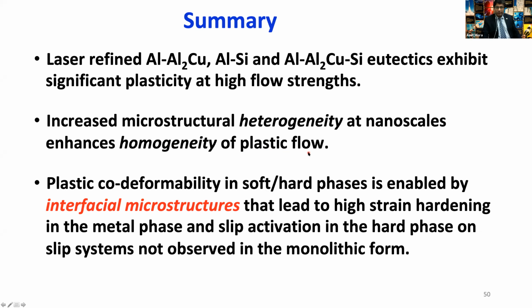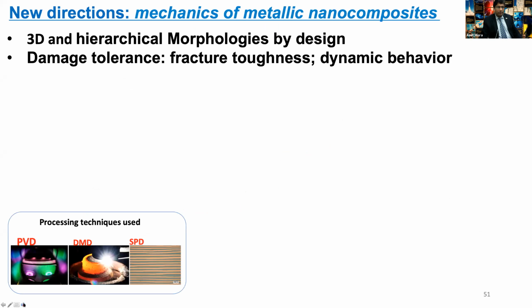In fact, you can increase the strength and you can increase the plasticity because you are able to somehow make the hard phase co-deform with the soft phase, as well as increase the strain hardening rate. So with that, I think this is my last slide. I'm going to stop and say that